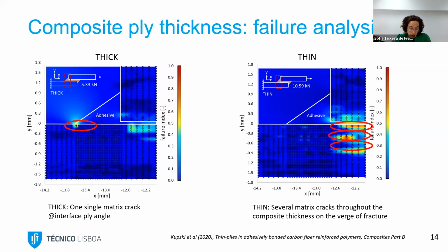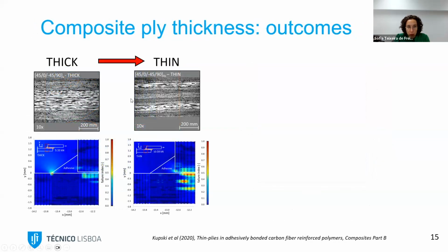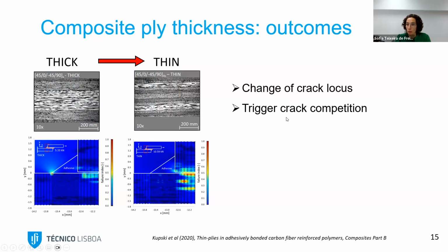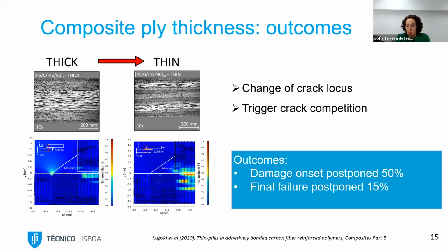So what is the result of these different fracture mechanisms for the thick and for the thin in terms of damage resistance of the bonded joint, which is what we wanted to see? When we go from the thick to the thin, we see that there is a change of crack locus. So the crack started at different locations, and when we use thin, there is a crack competition between different areas of the material. What is the result of this? The outcomes are that the damage initiation is postponed by 50% when we use thin, and the final failure is also postponed by 15%. So just by changing the ply thickness of the composite, we managed to increase the damage resistance of the bonded joint.